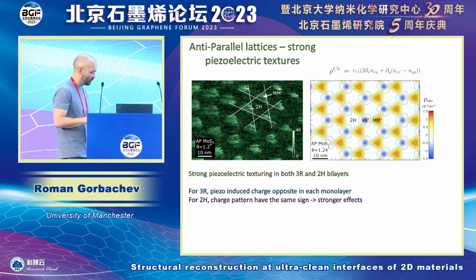The reason you have quantum dots appearing is because of the strain. So when the lattices click, they do it by creating strain. And strain in piezoelectric materials creates piezoelectric charge in the lattice. So that charge gets screened by free electron carriers, and that is why you're creating little quantum dots locally. There is a whole lot of papers about beautiful optical properties of this system. I'm not going to touch that, but there is so much research and very high impact papers on this. This really is an interesting system and worth looking into.